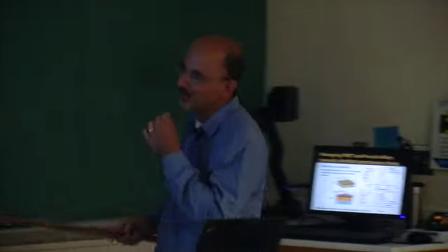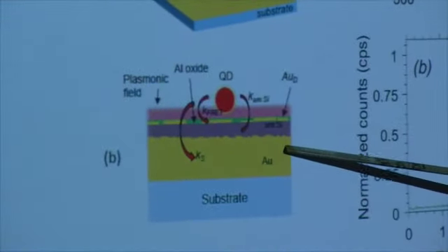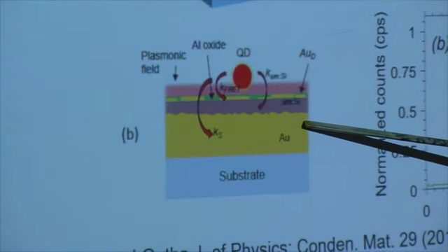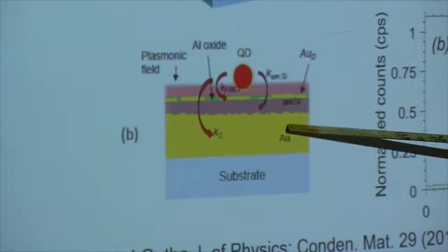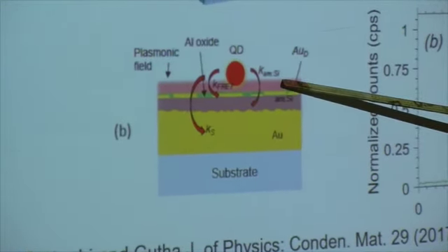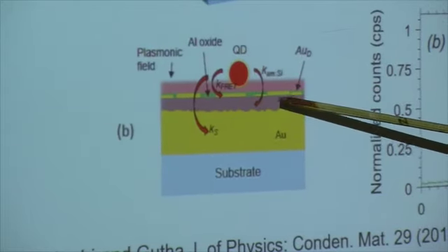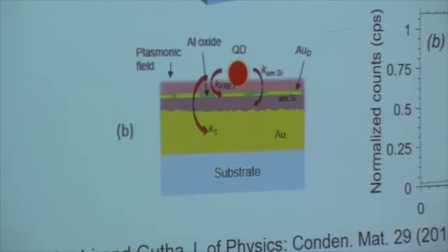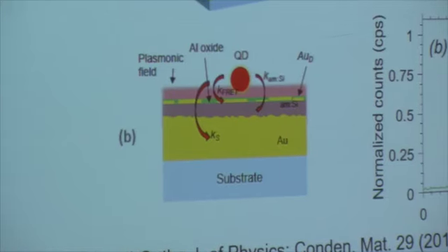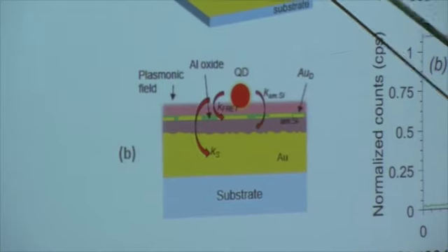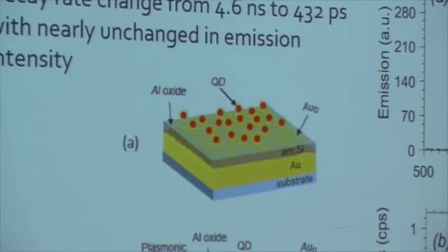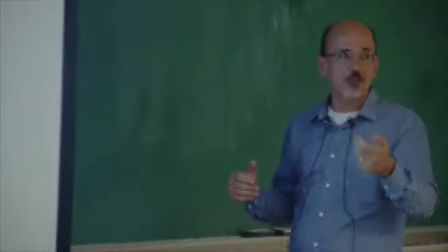So here is what we have done. We start with a substrate and a gold. This is a thick gold, which generates a good amount of field enhancement. And this purple color that you see is an illustration of how the field goes, how far it goes, and influences the quantum dot. Then in the middle, instead of silicon oxide, we put amorphous silicon with a sputter. On top of that, we put a very tiny layer of gold, maybe about 0.5 nanometer. 0.5 nanometer of gold doesn't generate large metallic nanoparticles. It makes very tiny, small nanoparticles. Later I'll explain why, but let me tell you what we got.